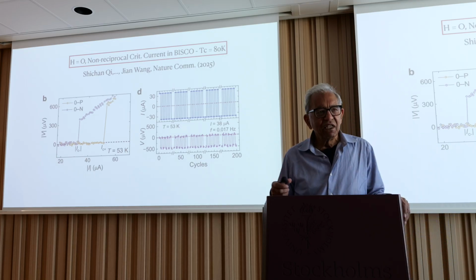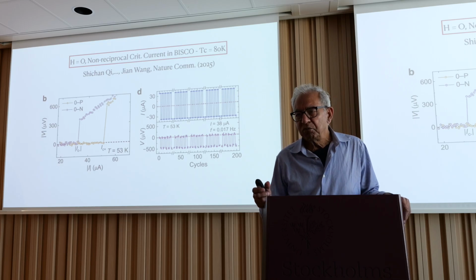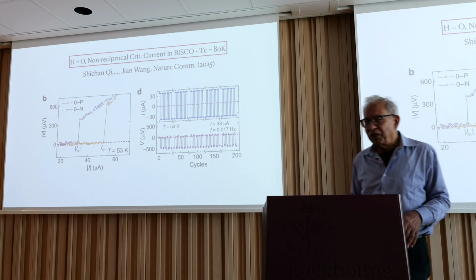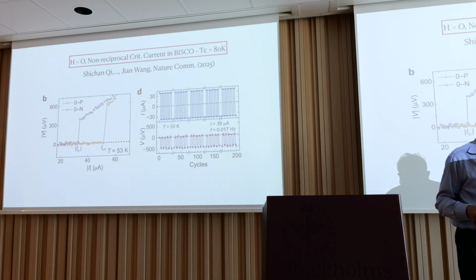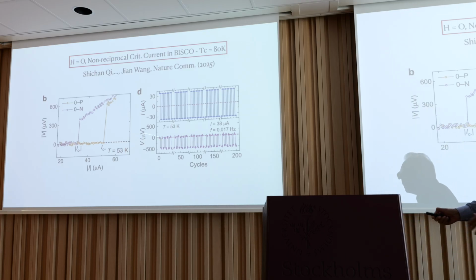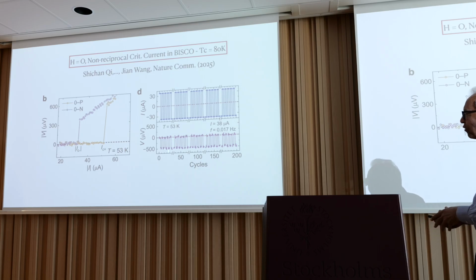non-reciprocal critical current is, it turns out, both a blessing and a curse, and I can explain why I say so, if there are questions on that. He very nicely then takes the sample and applies an AC current at a low frequency, positive, negative, and he's somewhere here, so he should observe in one direction 0 resistance, and in the other direction finite resistance, and that's what he observes.